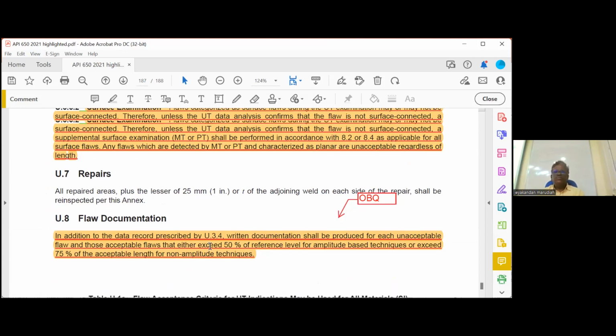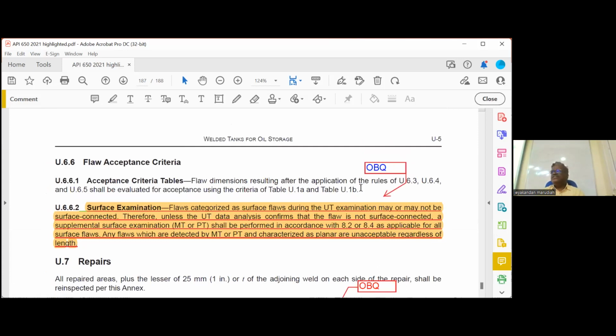Now there is one more point. This is important. Suppose you are doing UT. When you are doing UT, you can measure the defect depth. Now the defect depth shows it is on the surface. Generally, the problem with ultrasonic testing is it can detect a defect accurately when it is deeper. But if it is on the surface, it will miss.